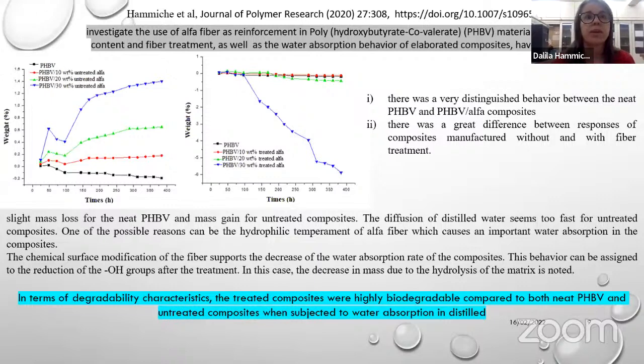From these figures, there are two different trends. There is slight mass loss for the neat matrix and mass gain for untreated composites. The diffusion of distilled water seems too fast for untreated composites. One of the possible reasons can be the hydrophilic nature of alfa fiber, which causes an important water absorption in the composite. The chemical surface modification of the fiber supports the decrease of the water absorption rate of the composite. Here, I mean that after treatment, we can decrease the absorption behavior.